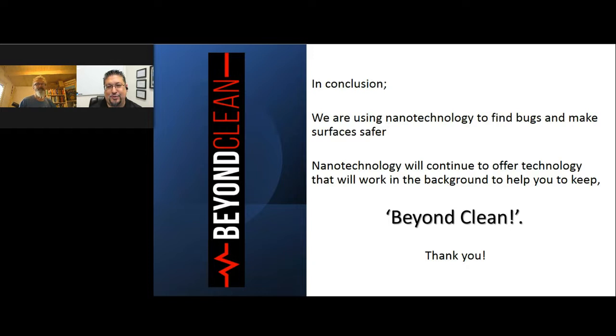Amazing. And then when a surface gets damaged or scratched, does that coating disappear? If you scratch the surface, because the coating has a very high micro hardness, you'll see a scratch and you'll think, oh, I've damaged our coating. But what typically happens is that you will see some damage in the underlying substrate, but typically the coating will go down into that scratch. And it's not 100% safe. If you have some high impact, then you might damage the coating. And what happens there is that if you can get water vapor through a pinhole, there might be a very small amount of delamination. But that's something you can work on. We're using physics to make the best possible coatings available.